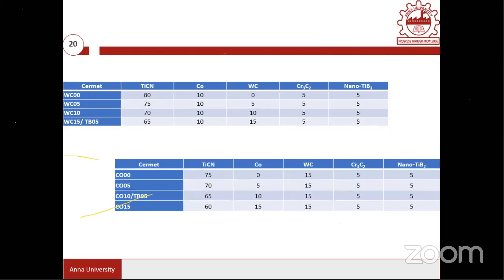And also here the WC is modified. We keep nano TiB2 constant and Cr3C2 constant. And what is the effect of tungsten carbide addition in this TiCN? That is represented here. So these compositions we are going to fabricate. And then another case where the cobalt concentration is changed, keeping the nano titanium diboride, Cr3C2 and WC concentrations common, and the cobalt concentration is varying.